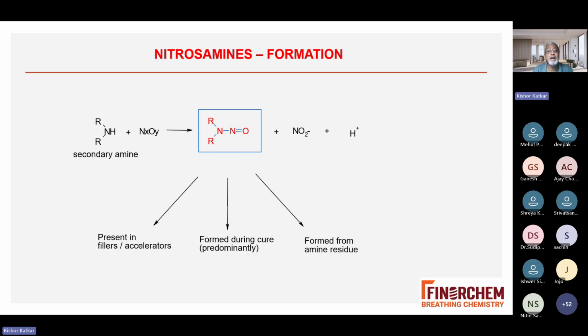nitrosamine, where it forms. Amines are present in fillers, formed during the curing time, and form amine residue also. So these free amines coming from the accelerators, or during vulcanization where it is brushed, the amine comes out, reacts with the nitrous oxide and forms a secondary nitrosamine. And these nitrosamines are carcinogenic, cancer causing.